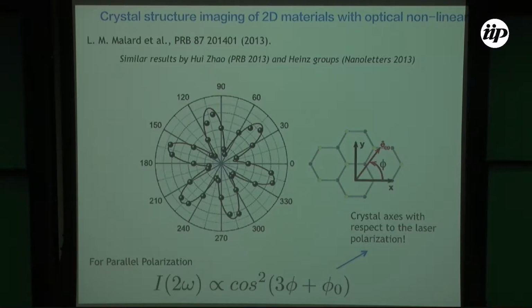We can calculate this because we know the crystal symmetries of MoS2. So we calculate the chi2 tensor and put it in that first equation from the previous equations that I showed about the induced polarization. Then we can calculate the intensity of the second harmonic. So you have this type of equation. You see that it's threefold, meaning that the crystal symmetries are threefold.